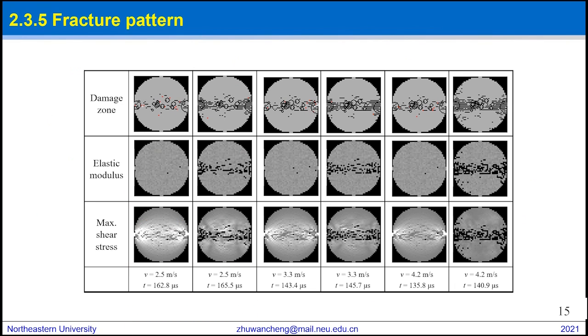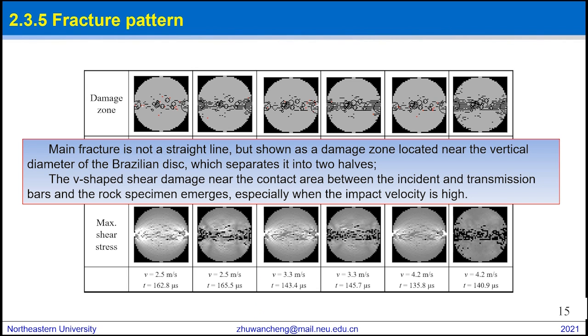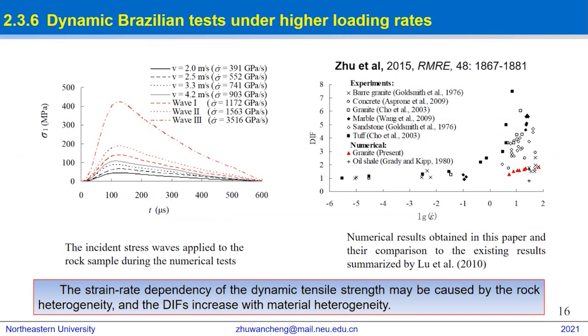Our results indicated that the main fracture is not a straight line, but shown as a damage zone located near the vertical diameter of the Brazilian disc, which separates it into two halves. And the V-shaped shear damage near the contact area between the incident and transmission bars and the rock specimen emerges, especially when the impact velocity is relatively high. The figure on the left shows three incident waveforms, wave 1, wave 2, and wave 3, with peak stresses higher than those produced by the pendulum hammer, our input for the numerical simulations.